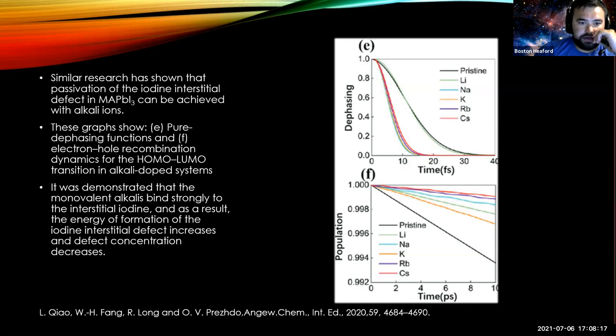And so again, you can see here the population changes of the different systems. And again, adding some of these alkali ions will drastically slow down the recombination rate, which increases carrier lifetime.